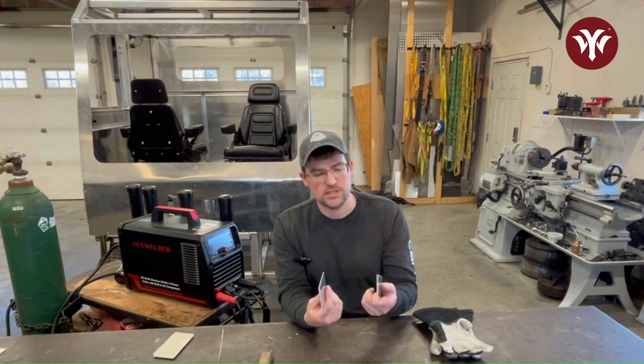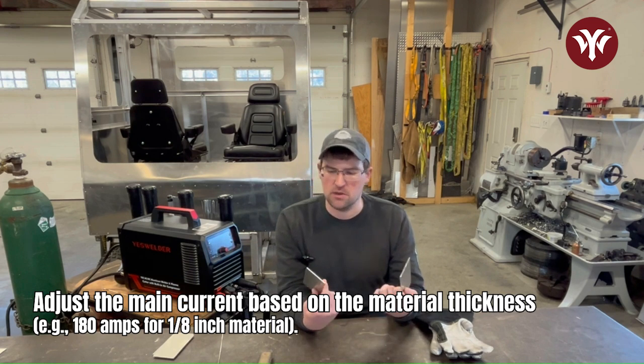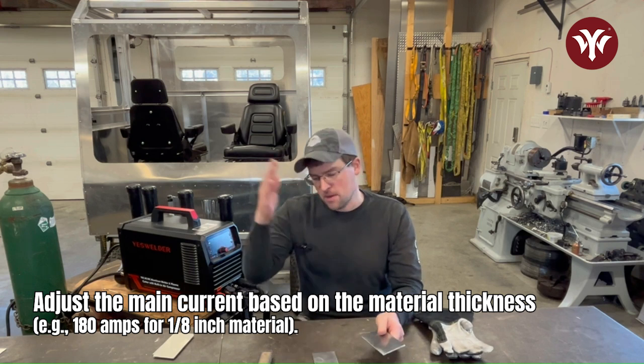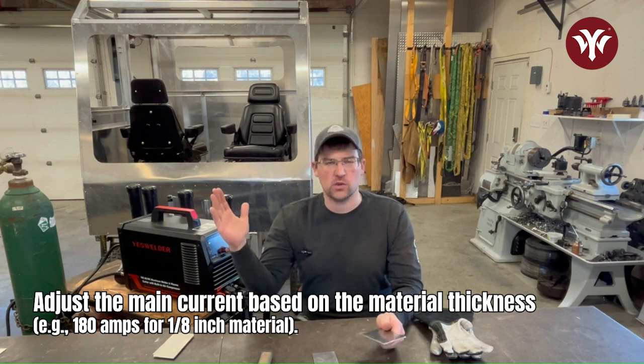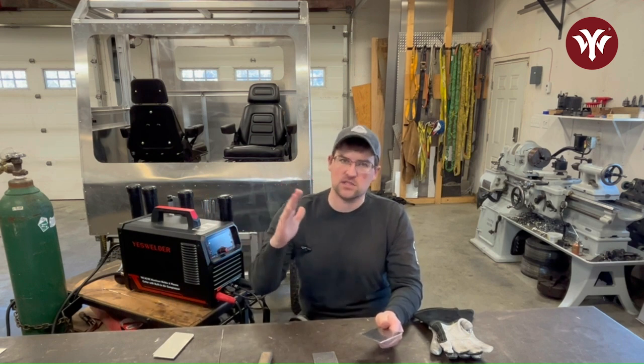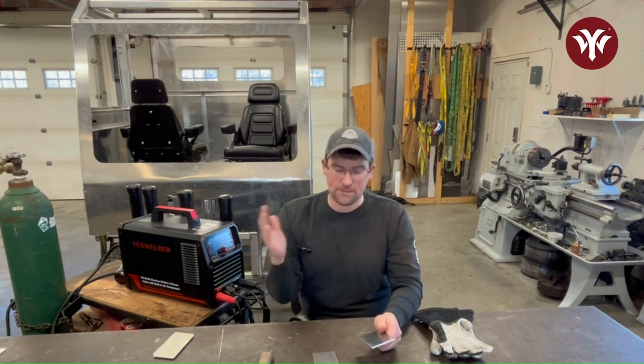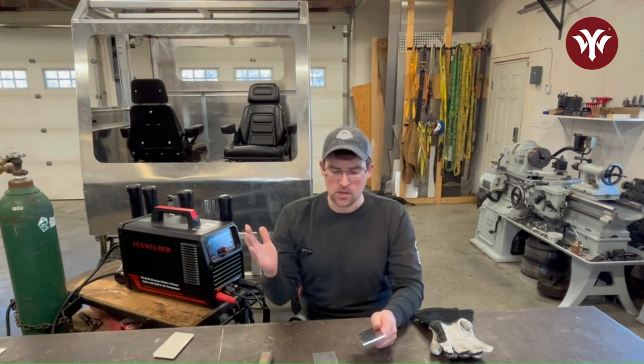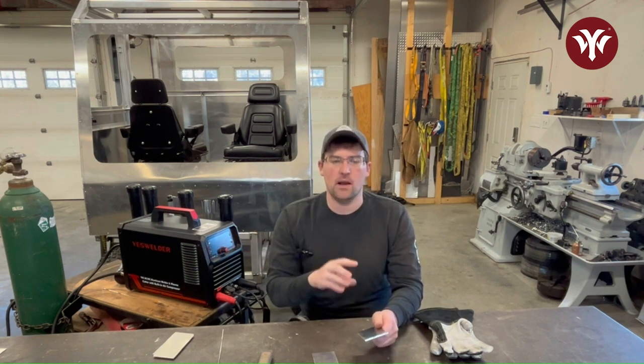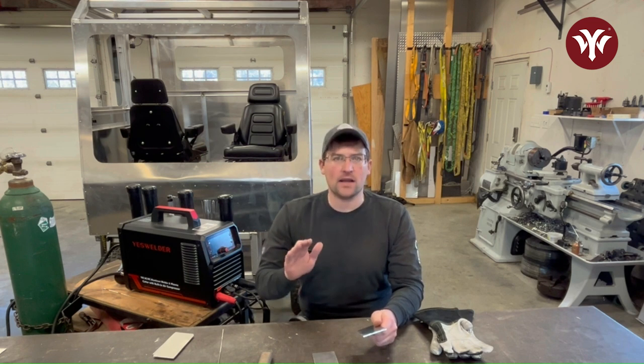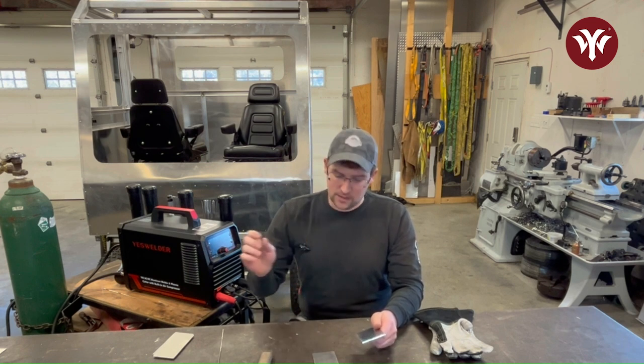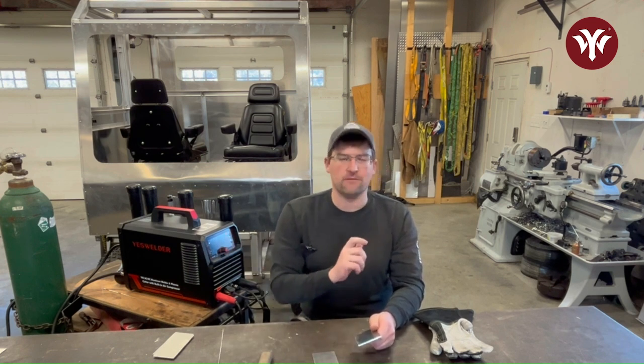Your main current is going to be pretty easy to understand. If we're doing 1/8 material, I'm going to set that machine to about 180 amps, which may be a little bit above where I'm actually welding. And then with that foot pedal, I'm going to dial in the current because I'm going to ramp up high to get my puddle started. But then as the base metal starts to warm up and my puddle's established, I'll back off the current a little bit so that I can get a nice puddle that flows and we'll have a really good bead.